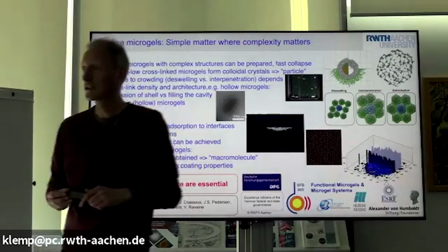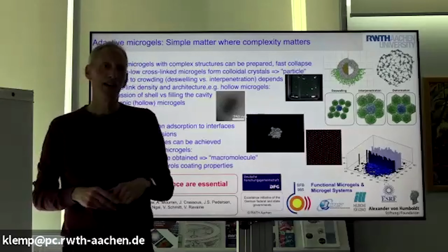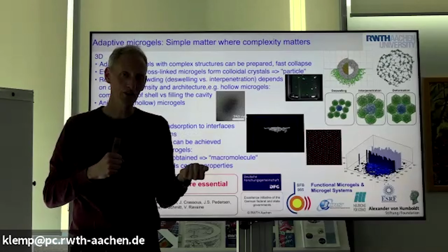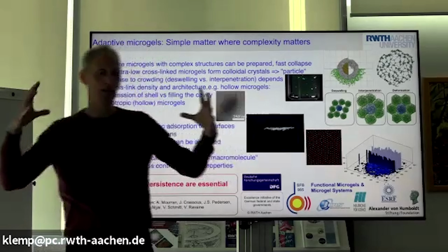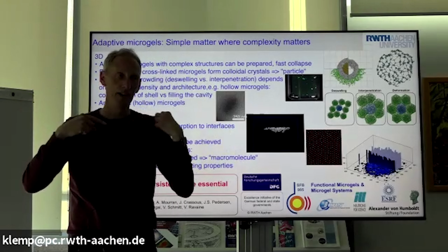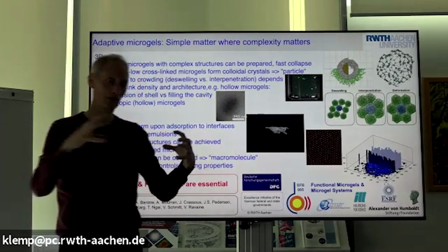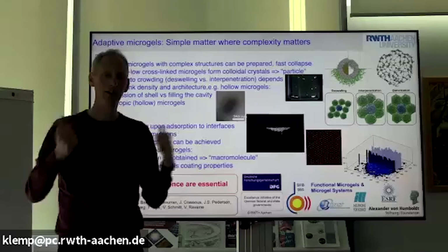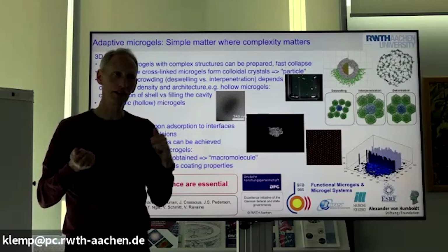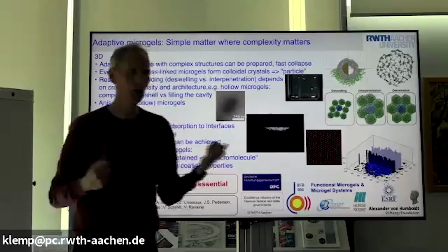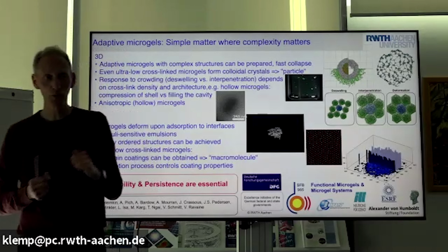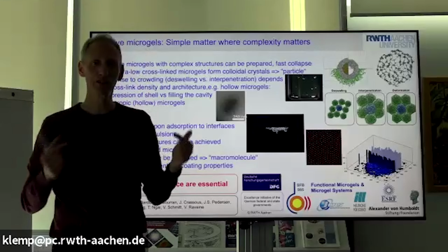We have now been making much larger hollow microgels where we go into capsules and they do show bending. You could imagine if you have a capsule, it could shrink or it could bend. And the small ones I showed you collapse. The large ones, I did not show you, they're very new data, they bend. So there is a size dependence in these properties, where especially the capsules show very different things. And we would like to tune the possibilities for charged microgels. We have charged hollow microgels, and we have good indications that we can lock charged molecules inside. So, different things to explore.